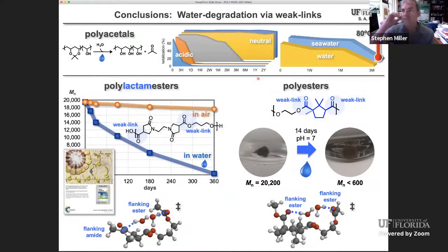So that just leaves me to some conclusions here. Our polyacetals are water degradable, certainly with higher temperatures. Our polylactam esters seem to be fairly water degradable if you're patient enough, even under neutral conditions. And we've shown some reason why that might happen. Theoretically, the polymer might be undergoing self-catalyzed base hydrolysis. That seems to be our best explanation presently.